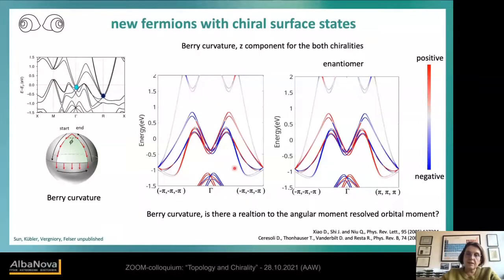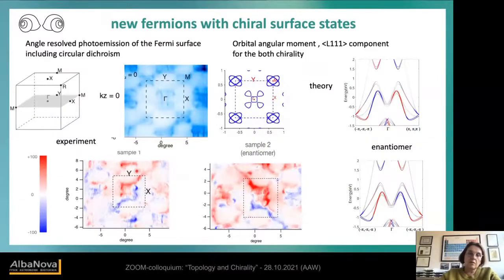And so this can maybe be shown in circular polarized photoemission. And we did a first measurement in collaboration. And you see here a simple Fermi surface with angle-resolved photoemission compared to the calculation. Again, very nice agreement. And then if you color it by doing the circular polarized light, you see nicely that the enantiomers behave again like a mirror picture. So we see a difference in the two enantiomers by the orbital angular momentum.